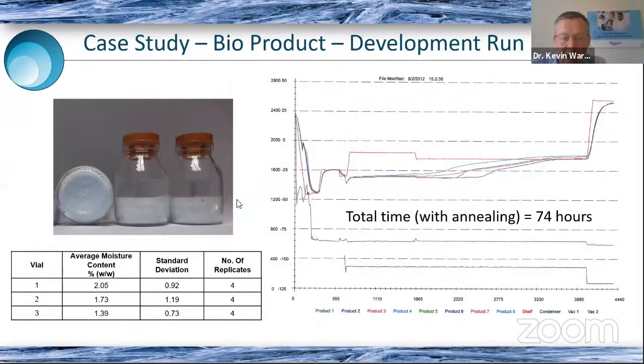And then in the final cycle, we just adjusted things slightly. So instead of going up incrementally, we figured that we could use a slightly higher shelf temperature early in primary drying, -10, and then we go back down to -15 when we know that the drying front is moving through the product and the drying speed is slowing down. So here it's still 74 hours like the previous one, but it's slightly more efficient at the beginning and slightly safer at the end. Slightly higher moisture content than before, but if we want to remedy that, then we will simply perhaps just need to extend secondary drying slightly to achieve a more robust cycle.